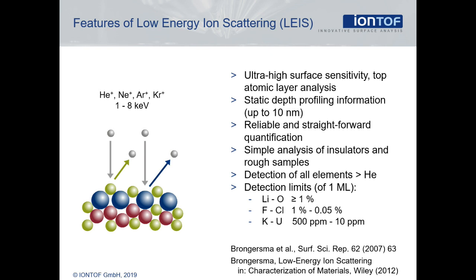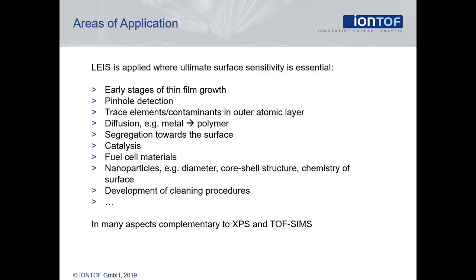Quantification is obtained by comparison to an elemental standard. However, this is not matrix dependent as it is in SIMS. LEIS is typically used in applications where ultimate surface sensitivity is the primary need. These can include pinhole detection, diffusion, catalysis, and fuel cell materials. In many aspects, LEIS is complementary to surface analysis techniques such as XPS and TOF-SIMS.